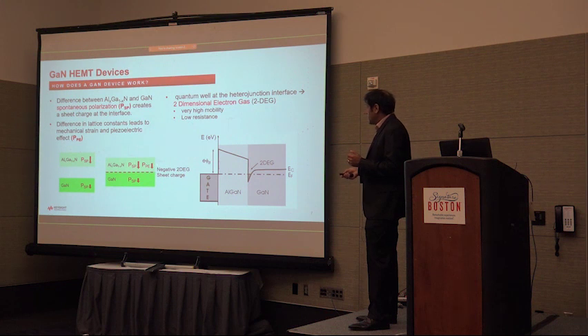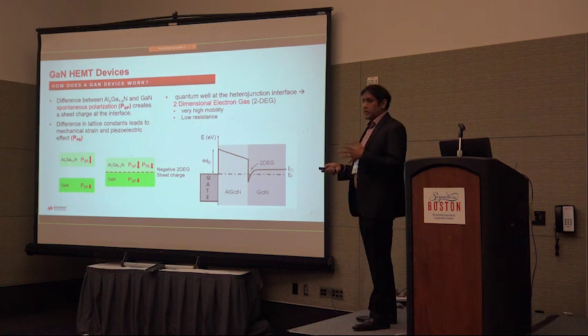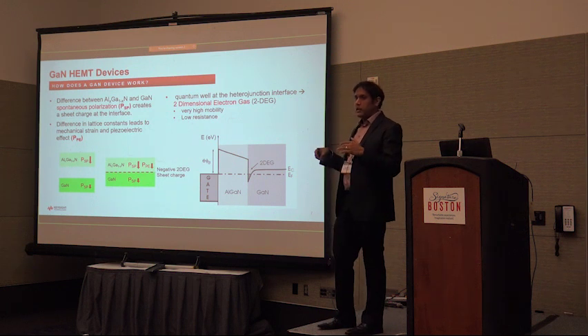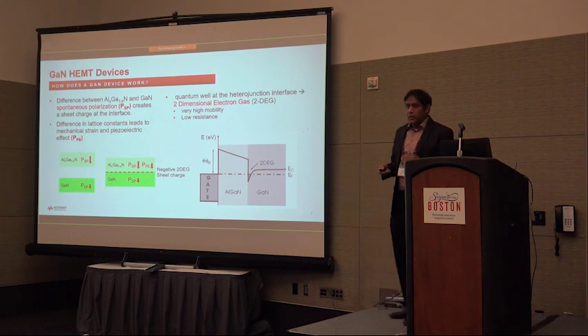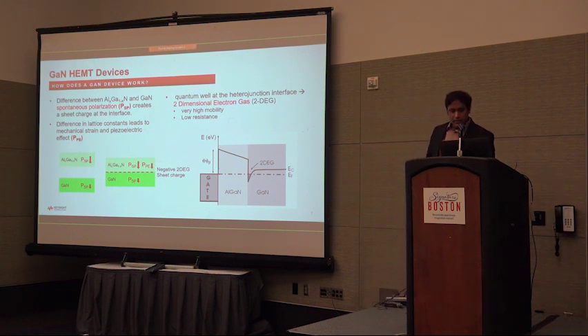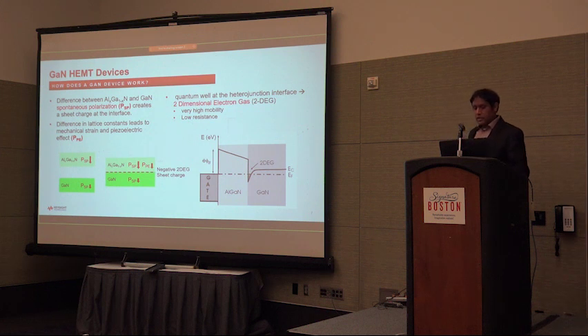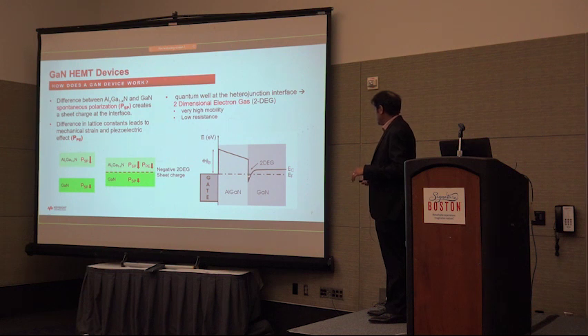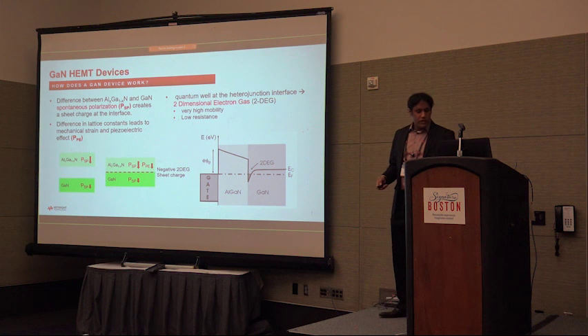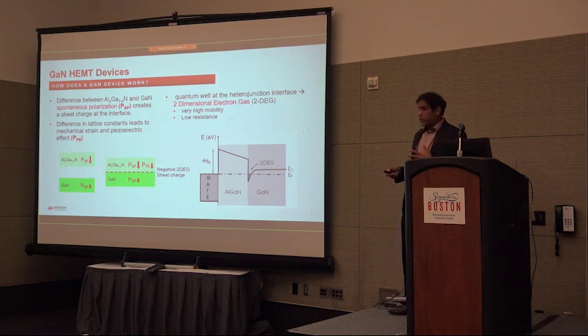While aluminum gallium nitride and gallium nitride have very similar lattice constants, we engineer them to not be exactly the same, which leads to mechanical tension between the surfaces. That mechanical strain causes a piezoelectric polarization — a change in electric field in response to mechanical stress. Combined with the built-in polarization, this creates a sheet charge right at the interface called the 2D electron gas. The conduction band falls below the Fermi level in this region, which is why mobility is so high.